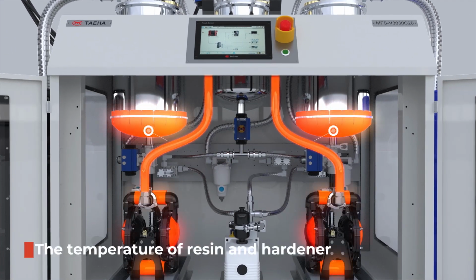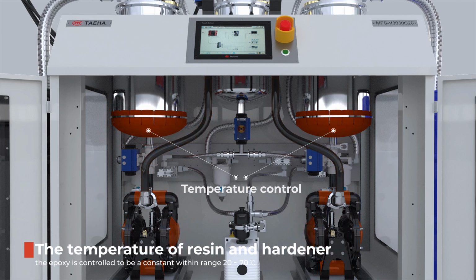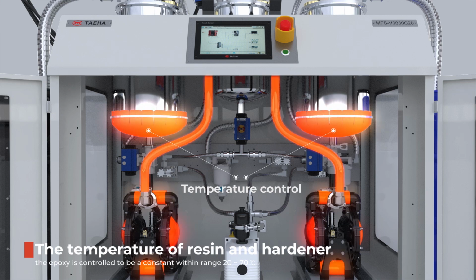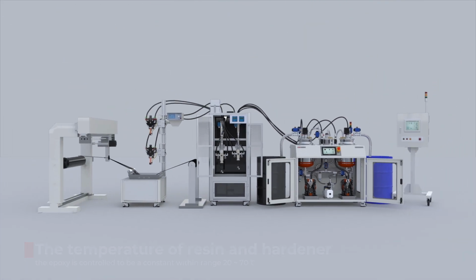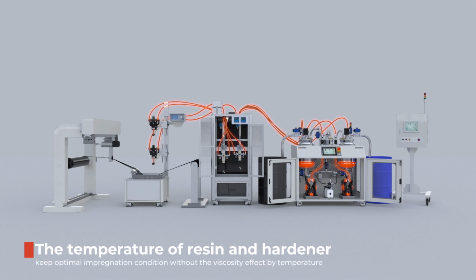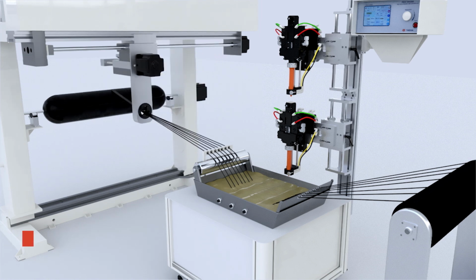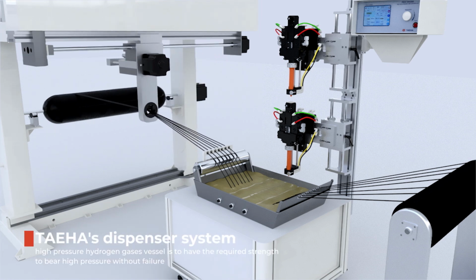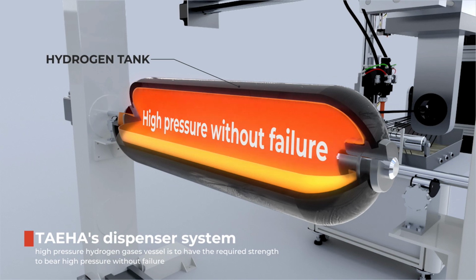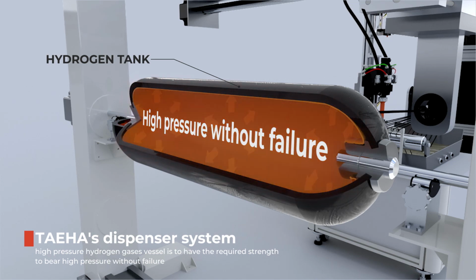The temperature of the resin and hardener of the epoxy is controlled to be constant within a range between 20 and 70 degrees Celsius to keep optimal impregnation conditions by eliminating the effect of viscosity caused by temperature. TAEHA's dispenser system supports the high-pressure hydrogen gas vessel in having the required strength to bear high pressure without failure.